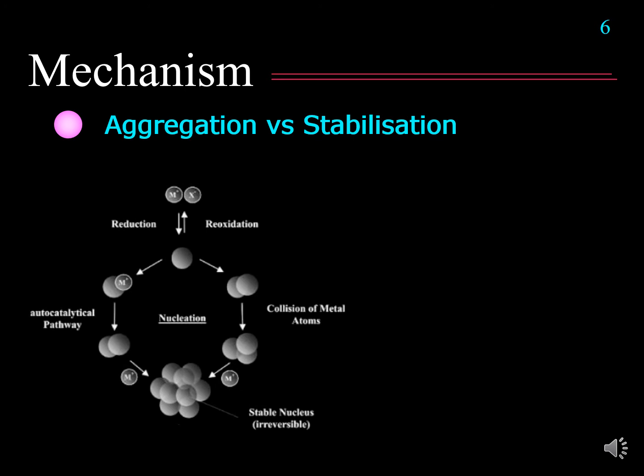The mechanism of formation of the gold starts from the gold 3+ up there, right? And then we have the reduction by sodium citrate, or we can use any other kind of reducing agent as well. And then the gold 3+ can be reduced down to gold 0. So gold zeros can then attach with themselves, okay, forming a bigger cluster of the metallic gold.